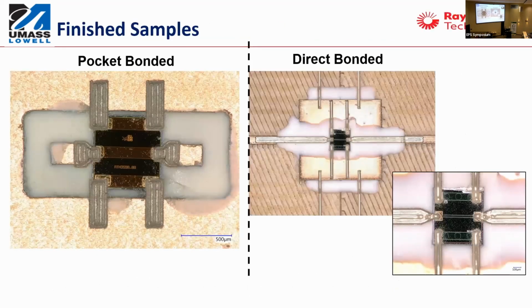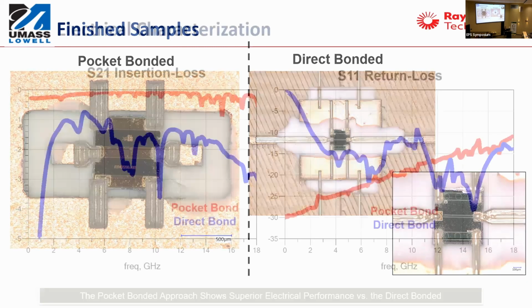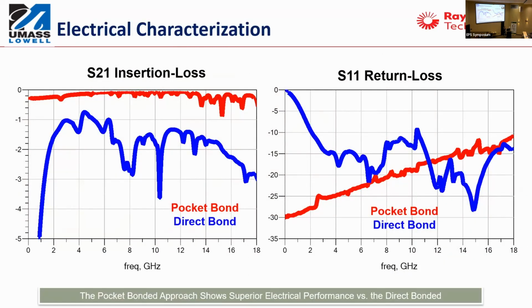And so this is some attenuator chips. We start with the cheap attenuator chips that we can get rid of if things don't work. So you can see pictures of what pocket bonded and direct bonded bare die chips look like. And then these were some initial results that we got, which showed that the pocket bonding got better results. Even though this might be the case, there are certain cases where, due to the geometry of the problem, we might end up still going with the direct bonding.